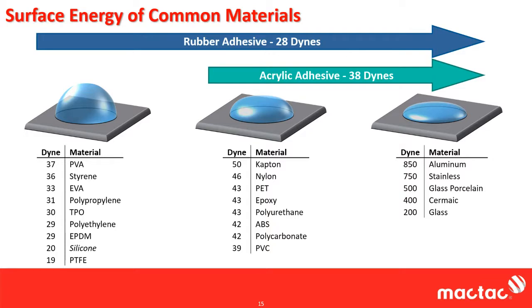Again, the rule of thumb is that you want your adhesive to be equal to or less than the surface you're trying to stick to. Rubber-based adhesives are far below PVA, styrene, and really below polypropylene and equal to polyethylene, TPO, depending on who's measuring it. It's for sitting equal to or less than. But again, the acrylic adhesive at 38 dynes is well above those surfaces. A straight acrylic just doesn't stick very well to them. You have to start getting into modified acrylics or LSE acrylics.